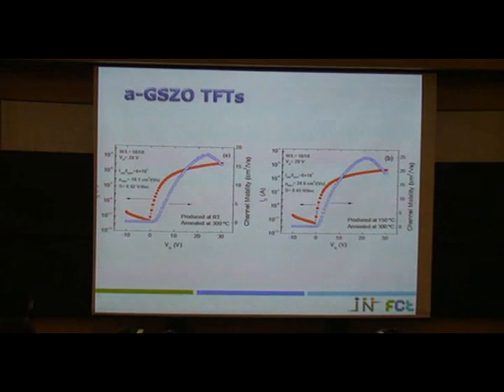And these are the results for the devices. Of course, the mobility is a little bit lower, so we can achieve mobilities of the order of 20, not so high as with the GIZO system, but they work properly, and maybe with some improvement we can also achieve higher values.